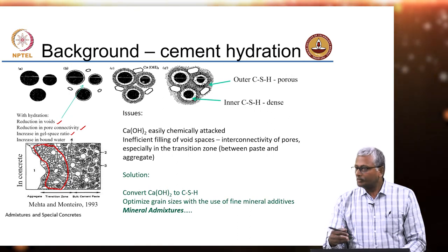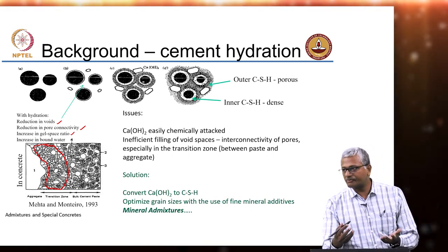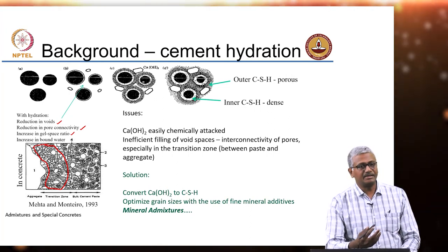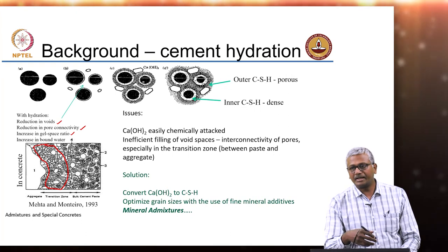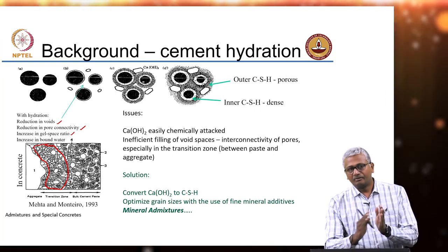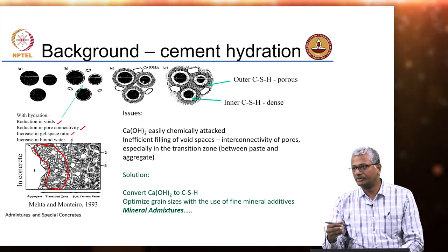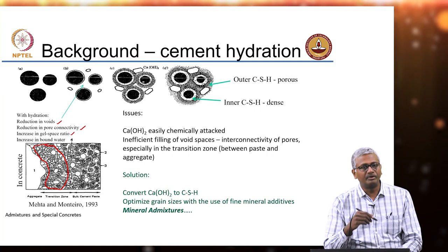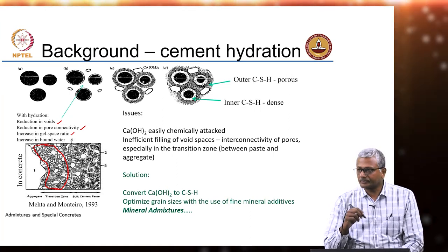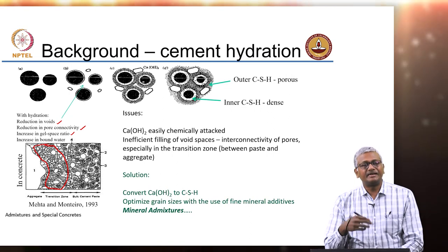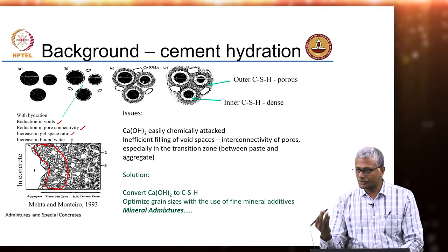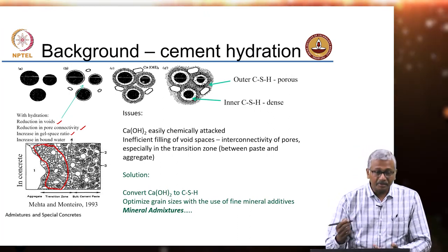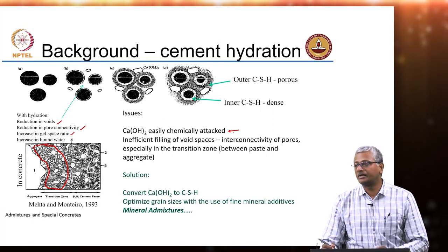Microstructurally, because of conditions favorable for crystalline formation, there is more calcium hydroxide in zones next to the interface. Further away from the interface you see a greater distribution of CSH and other hydration products, but at the interface you see a lot more calcium hydroxide. Calcium hydroxide is a good solid material — it blocks pore spaces and contributes to strength, but it is also a phase that gets easily chemically attacked.